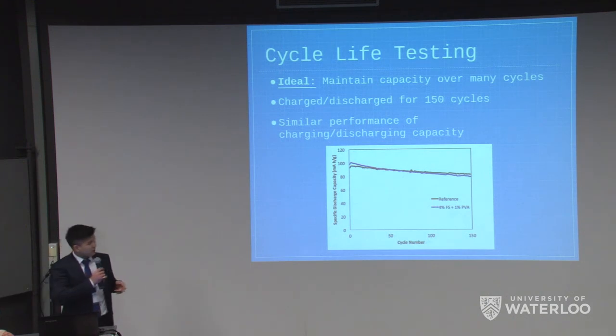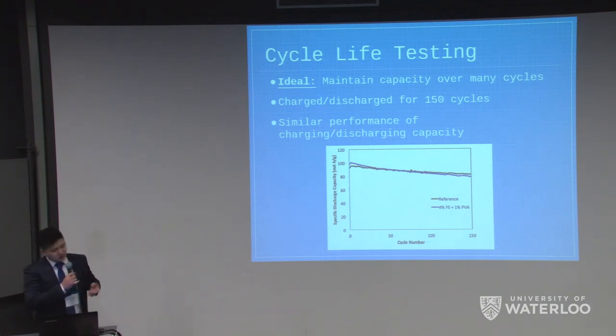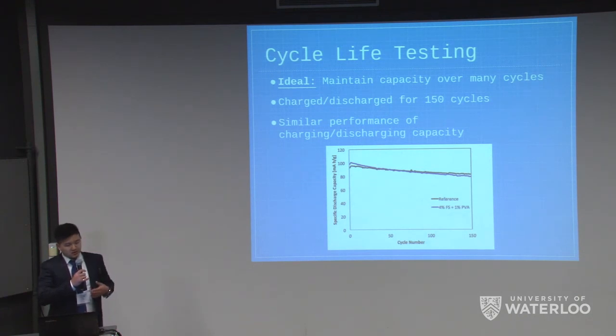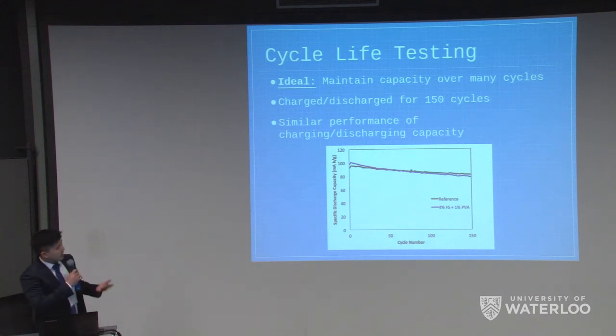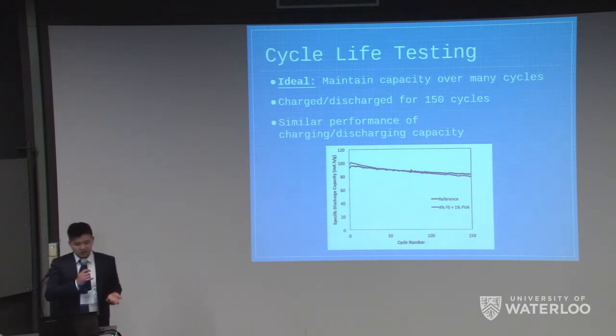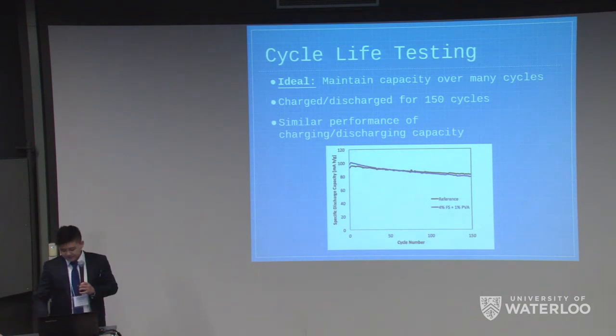We did this cycle 150 times for the liquid electrolyte and our designed electrolyte. For the fumed silica, we couldn't even fabricate it because it was too thick to be absorbed in the glass mat. But the result between the liquid electrolyte and our additive shows similar performance of charging and discharging capacity.